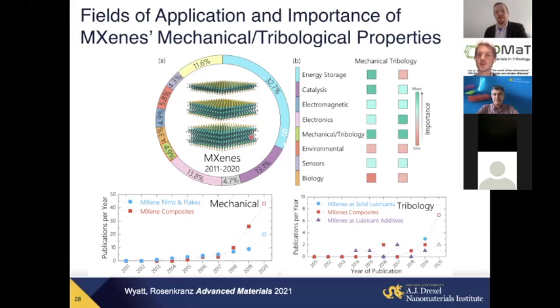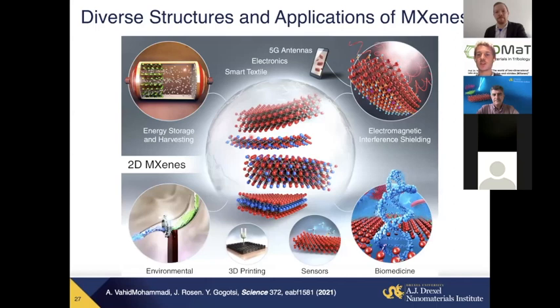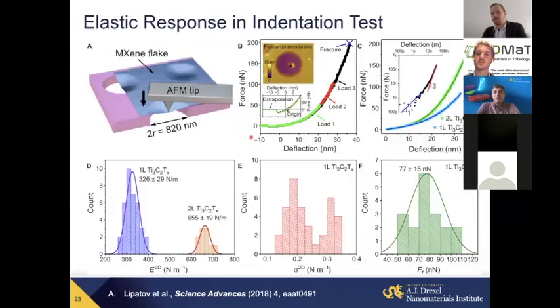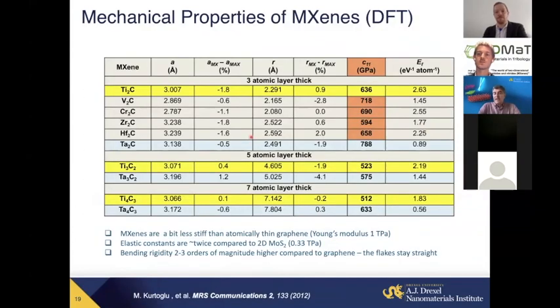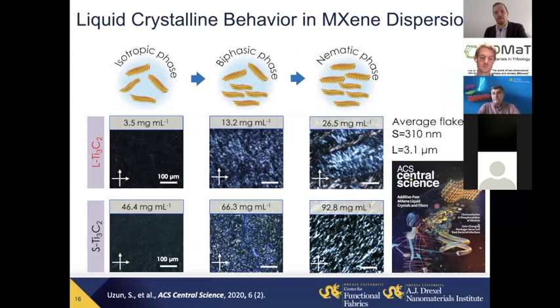Very good. Another question regarding 3D architectures. Just like 2D or 3D graphene materials, can we obtain different shapes of MXene layers by using some surfactants or chemicals? Yes, with the only difference that you don't need surfactants or chemicals. But yes, it's possible. I didn't talk about it today, but you can treat MXene just like many other materials. Unlike graphene, you don't need surfactants because it will disperse in water or also many solvents. So you can do, for example, freeze drying, and you will produce an aerogel. You can incorporate it inside hydrogel polymer matrices. From the liquid crystalline materials that I showed you before, we can even draw pure MXene fibers. And actually, this is what the cover of ACS Central Science for this work shows. So yes, it's possible to produce 3D architectures in a variety of different ways.